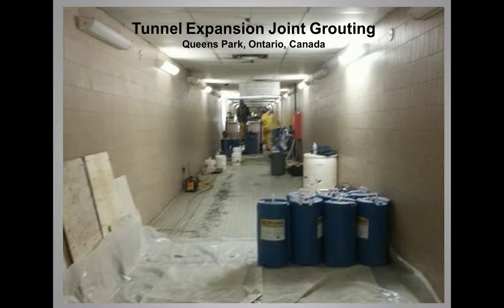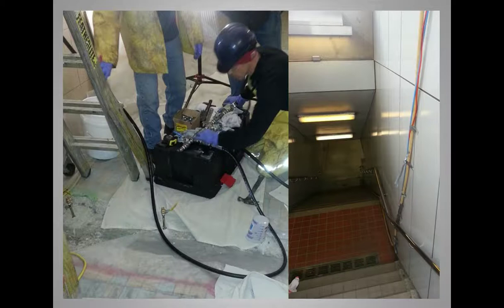When severe inflow conditions are injected with a poor material selection, the leaks usually persevere. Typically, cement grouts have a slow set time and do not effectively shut off leaks unless using appropriate admixture or sometimes flash setting agents. With the right additives and flash setting agents, even cement grout can be injected and set in minutes or seconds. This photo illustrates the injection packers installed directly into the rock mass. The angled drill holes were strategically drilled to intercept the flow path and to target the water source for injection grouting.